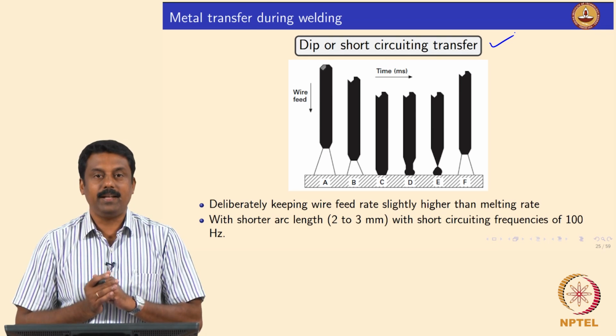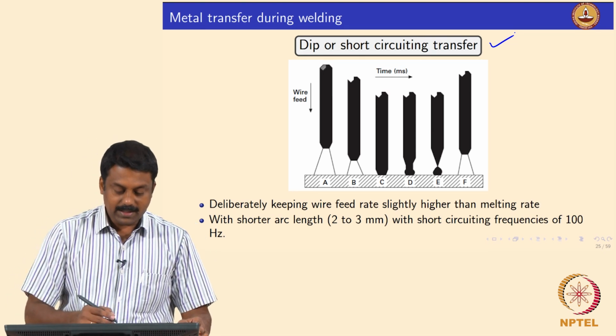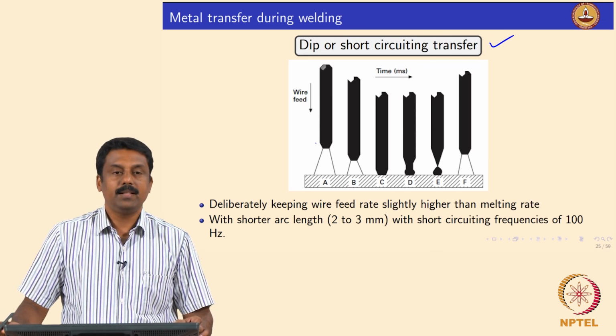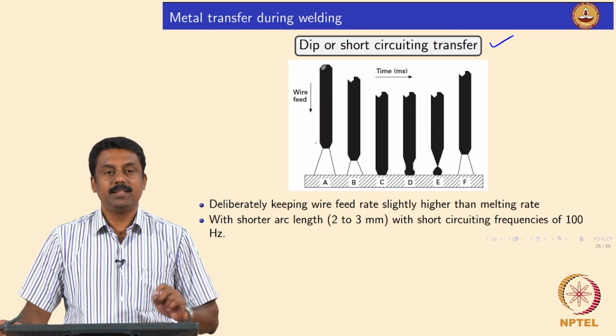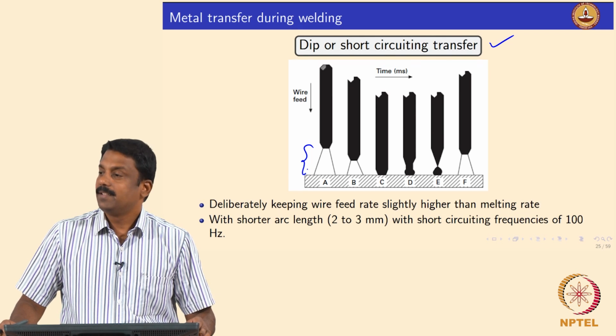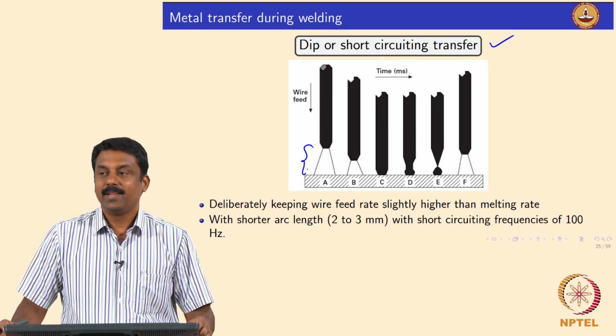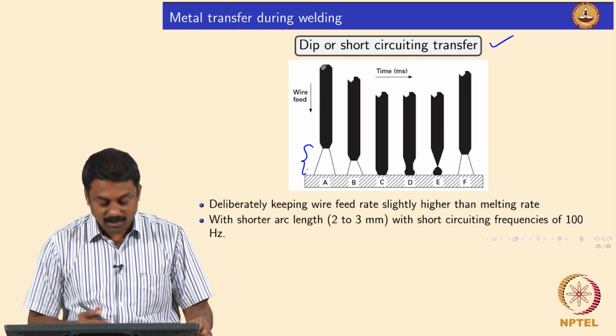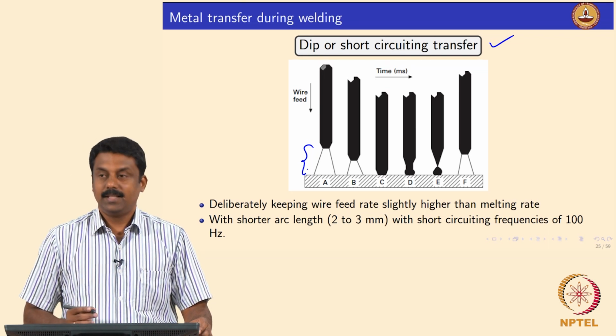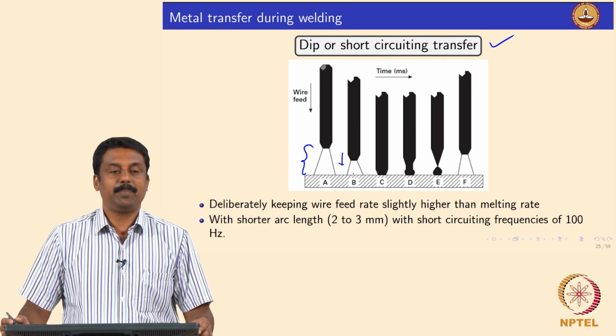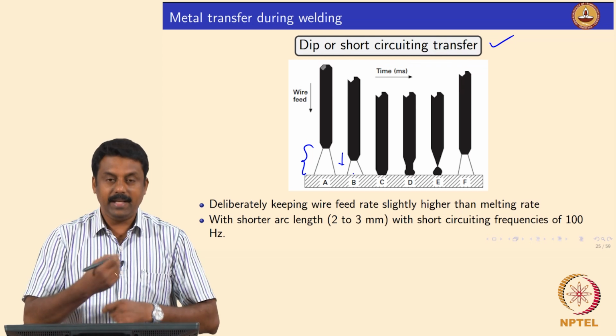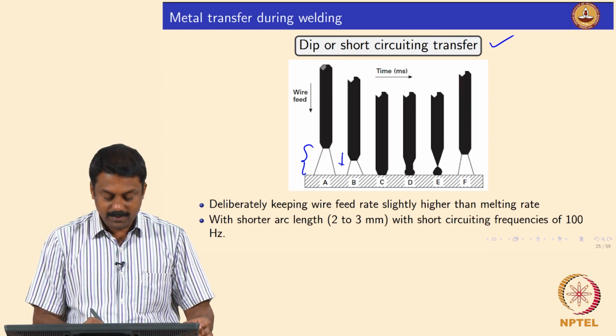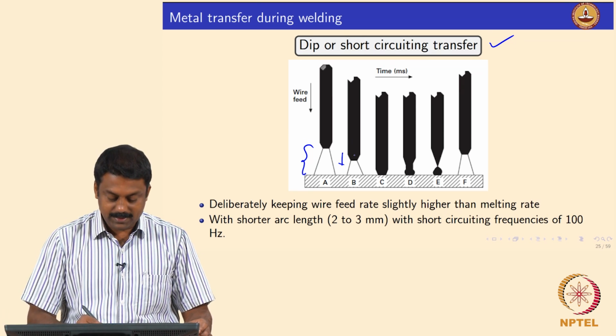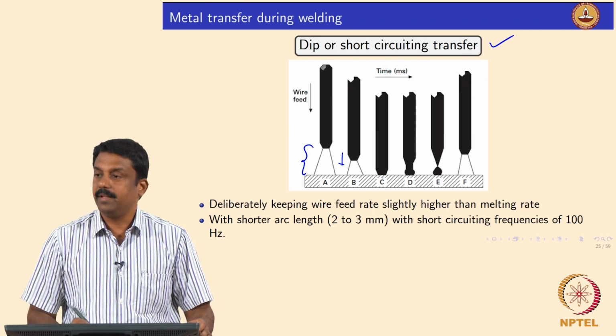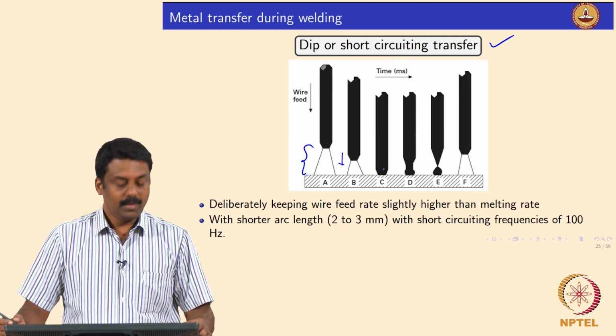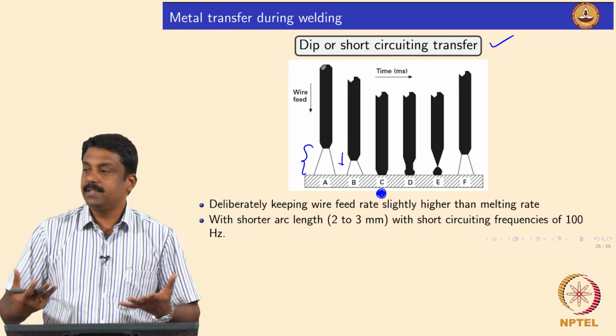Okay. So, the one example schematic I show you here from Prof. John Norrish's book. So, basically what we do is, wire is continuously fed, is not it. If the melting rate is equal to the wire feed rate, what happened to the arc length? If the melting rate is equal to the wire feed rate, arc length becomes constant, is not it. But you can also carefully manipulate the feeding rate such a way that you slowly bring the wire towards the workpiece or weld pool. Okay. So, increase the speed of wire feeding such a way that you can bring the filler to the workpiece and establish a short circuiting, right. It is clear. And once the short circuiting happens, you also increase the current,